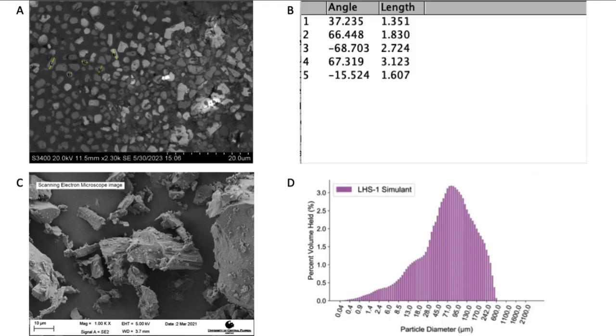The materials team verified the creation of metal matrix composites by manufacturing them both via mixing and sandwiching the regolith and metal. Pictured here is a high temperature mixture of 10 weight percent regolith and aluminum. Notice that the average particle size from our sample is much lower than expected from the regolith particle size distribution. This is indicative of a thermite reaction which would allow unique tuning of material properties.